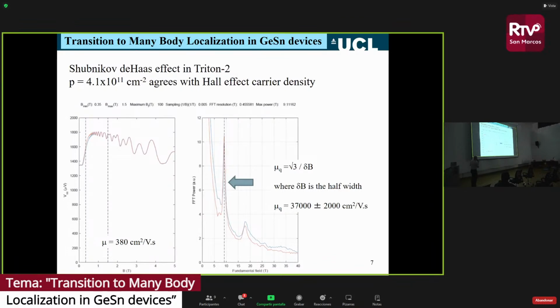We see a very, very clear magneto-oscillation. If you work out what the mobility is, it's a few hundred. It's about 380 centimeters squared per volt second. If you look at the quality of these quantum oscillations, we see spin splitting. We see some kind of weak anti-localization, possibly some geometric magnetoresistance, the spin splitting. So it's all very, very high quality magnetoresistance.